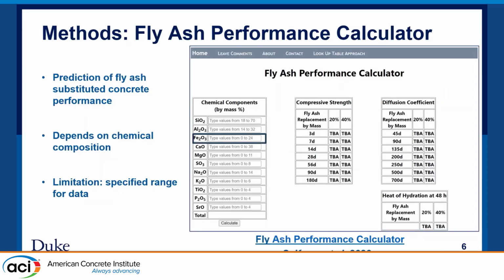For the start of the research, there is a fly ash performance calculator prepared by Dr. Tyler Ley, and we use this calculator to predict the performance of fly ash concrete with different percentages of coal combustion ash in the concrete. It then gives the data relative to the 0% fly ash concrete, for different days. This depends on the chemical composition of those coal combustion ashes.